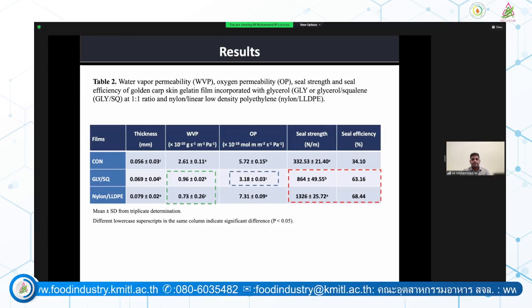The experiments showed the thickness of the film, the control, glycerol, and the commercial packaging, where the control was the least thickness. And we can see the water vapor permeability was much higher for the control films compared to the glycerol and nylon. The squalene incorporated film had lower water vapor permeability, close to that of commercial packaging. So this was a good indicator for using it as a packaging material. And we can see the oxygen permeability. Control has this much oxygen permeability, and squalene has lower oxygen permeability compared to all, including the commercial and LDPE packaging.